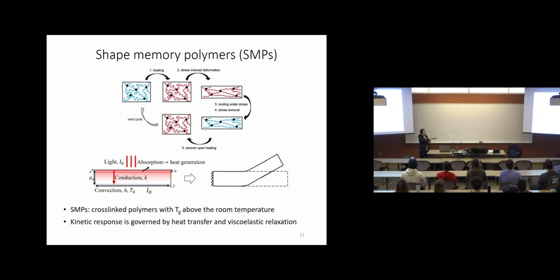When you shine light, you can generate heat. Typically, there's also a light intensity decay in the thickness direction, which will create a temperature gradient. Then you also have thermal conduction, and some thermal loss on the boundary. Moreover, when the temperature at a specific location is above Tg, the material can undergo viscoelastic relaxation. So if you originally pre-stretch the material, then whenever the temperature is above Tg, it can relax and shrink back to its original shape.